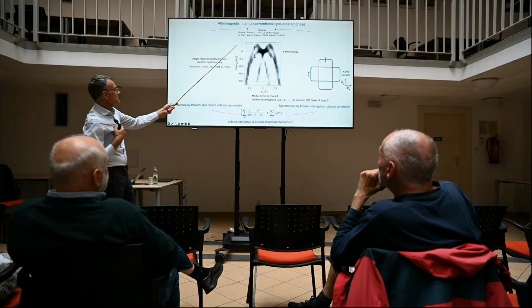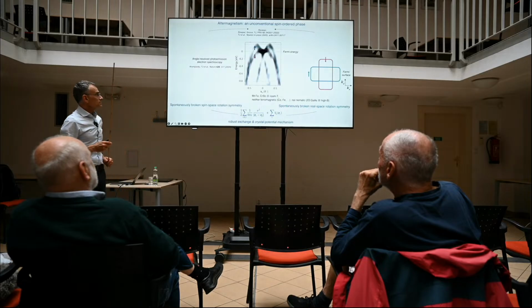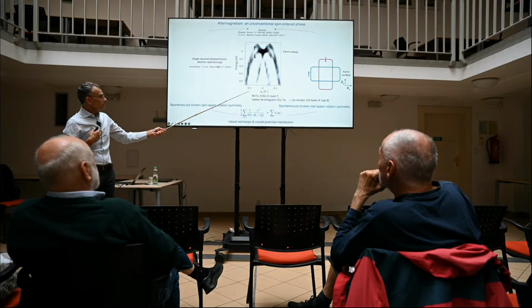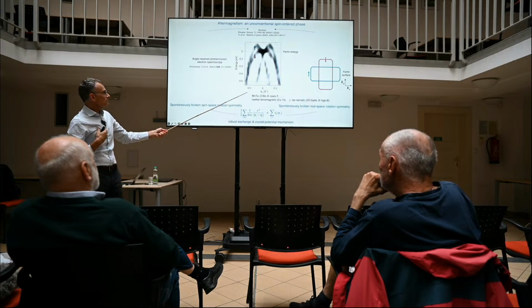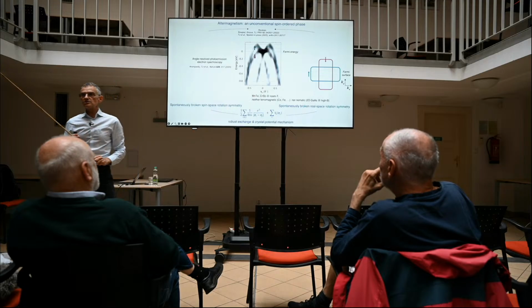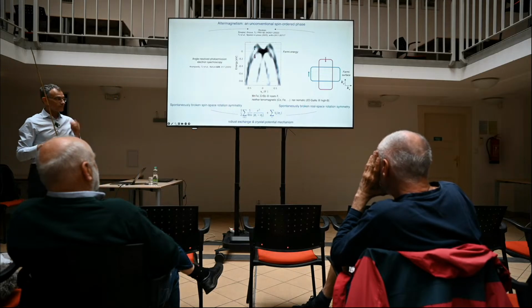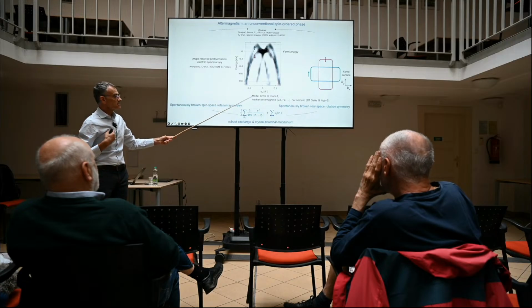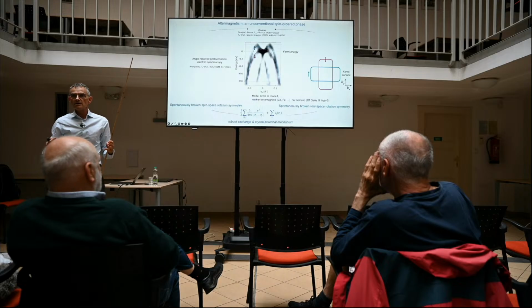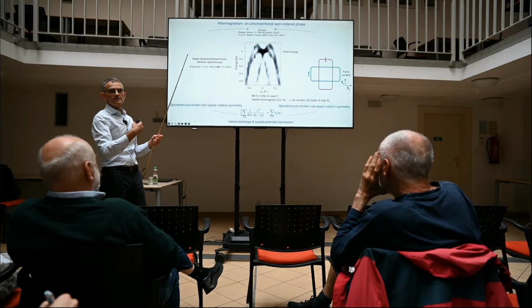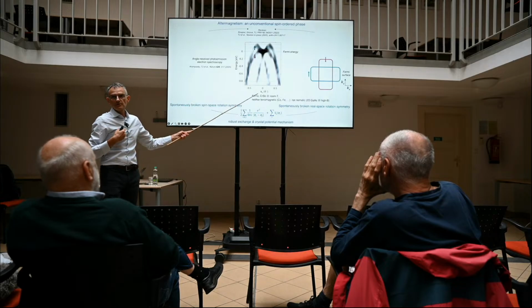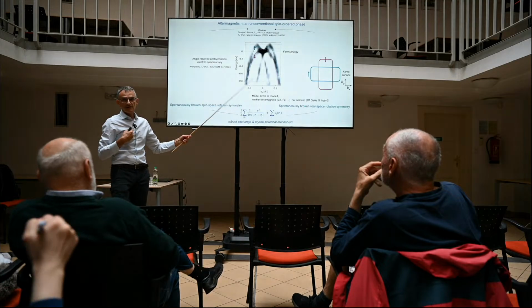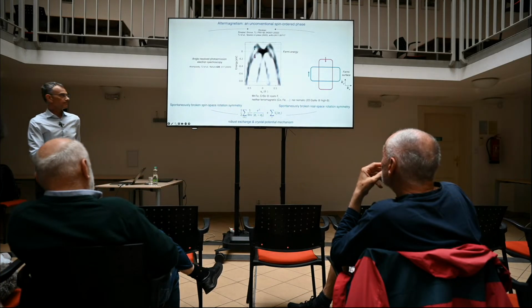This is the direct experimental observation of such a phase in real materials. And the real materials are manganese telluride, chromium antimonide, and there are a few other materials in which there has also been a direct observation of this type of magnetic ordering. And what I want to emphasize here is that these are not obscure materials, complicated compounds, something that people had to artificially synthesize or didn't know of. These are very simple binary compounds that people have had in their drawers for decades, including us, I have to admit, without knowing anything about them. And they also order at room temperature, which tells you that the altermagnetic ordering can be robust.